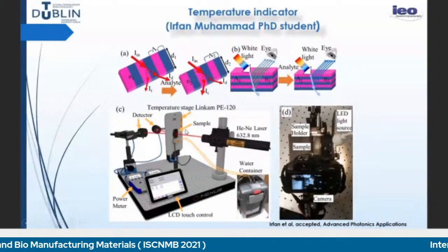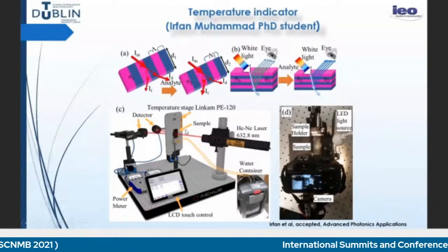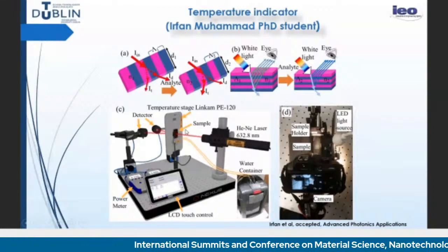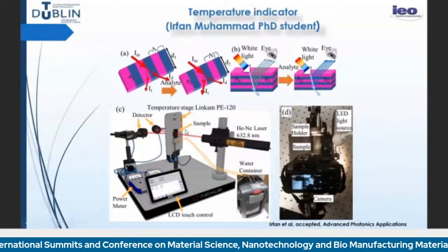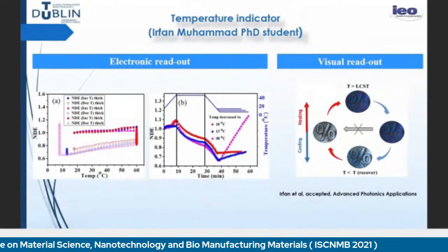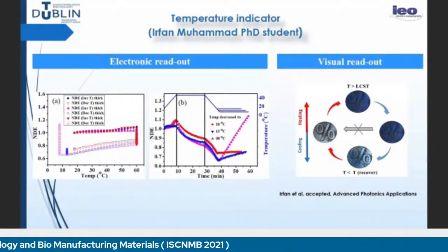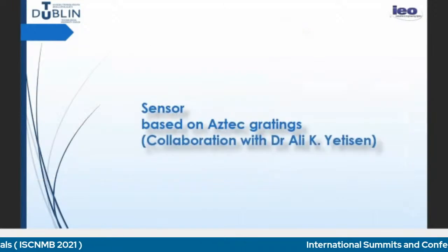And in this composition, we found out that you need to go to 8 degrees in order to start recovering the original color. And this is interesting because for some goods, you would like to know whether they have been exposed to high temperature above 32 degrees, and this could be an indicator, just a color indicator, of whether this has happened. We have also worked on Aztec gratings.